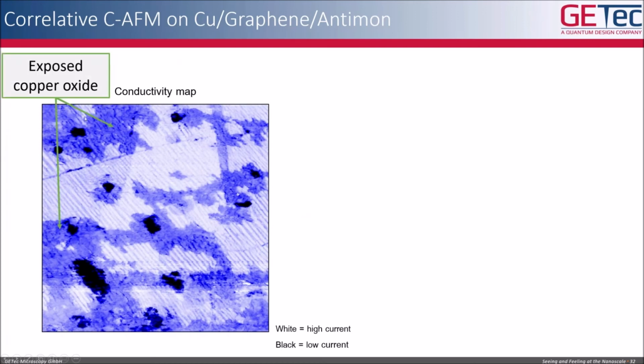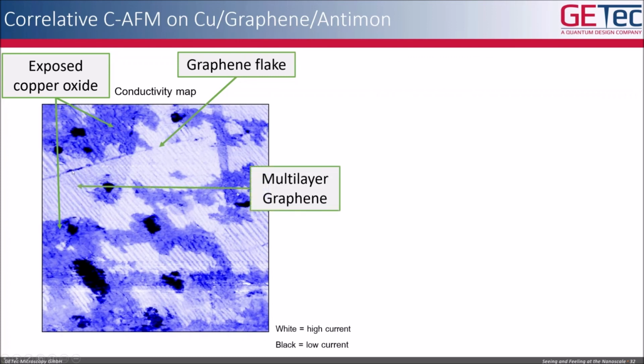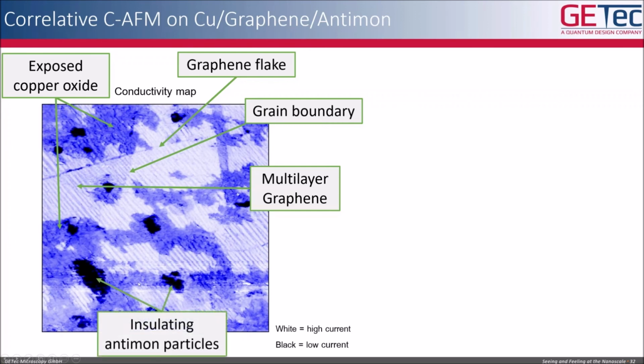You can really see these exposed copper oxide parts with these dark blue parts. You see a graphene flake here, which is bright white because it has the highest conductance. Then you can even see something a little less white, which is probably a multi-layer graphene. You can also see this grain boundary section between the two different graphene regions, and there are some insulating antimony particles, which are black in the conductive signal. So there's a lot of information you can extract from this correlative conductive image taken inside the SEM.